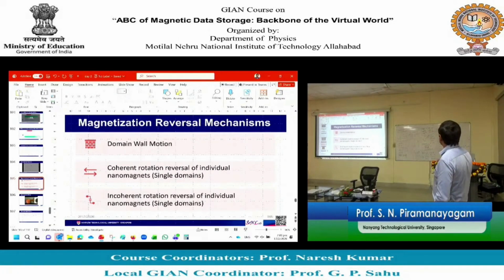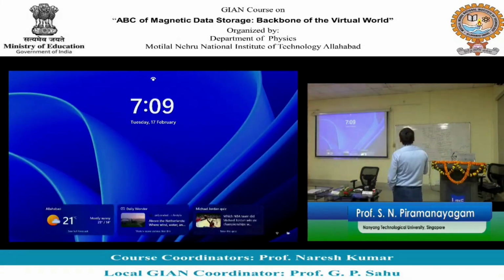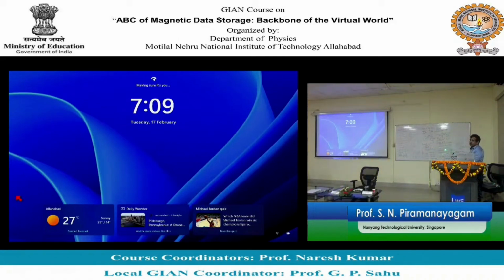in the domain walls there is some energy. So, you increase the domain wall energy. Ultimately, whether the system forms magnetic domains or not depends on which one will reduce the overall energy. For example, if you reduce the magnetostatic energy more than the energy you need for forming a domain wall, then domains will form. This is like you do not mind losing 100 rupees if you gain 1000 rupees, right. Then you do not mind doing that. So, in this case domains will form.